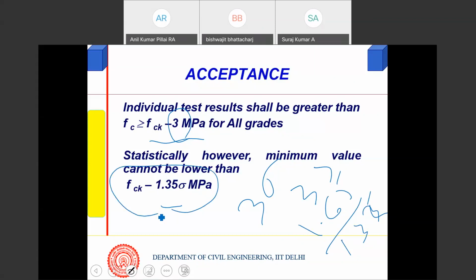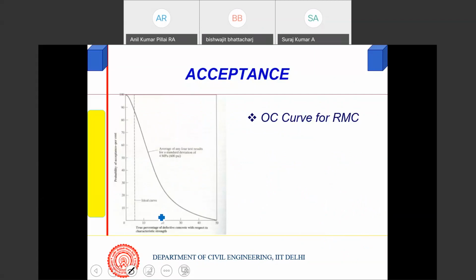Operating characteristic curve, OC curve, for ready mixed concrete, because 5% is the acceptance by the client. But there's a probability that it will be rejected, although you have actually given 5%, because that probability is still there. Ideally, if the defective is more than 5%, it should be rejected, so the probability of rejection is 100%.